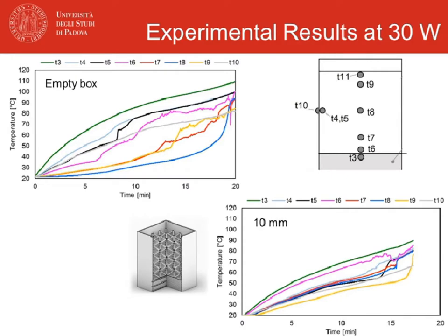So on the top of this slide you have the empty box. On the right bottom corner you have the best 3D periodic structure, and you see from this image that the temperature inside the empty box is quite scattered. So there is a great difference between, for instance, T8 in the center and the T3. There can be a difference up to 60 degrees C. Differently, in the system with the periodic structure, all the thermocouples are much closer to each other, and the difference is always kept below 20 degrees, almost 20 degrees, something like this.